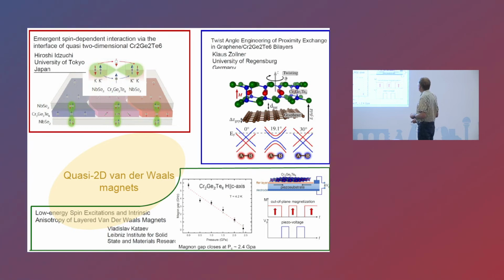Another interesting application of the single layer of chromium germanium telluride was discussed by Klaus Zollner from the University of Regensburg in Germany, where he showed that when this layer is put on the graphene layer, and the twist angle between these two layers is changed, it leads to a very interesting change in the band structure of the graphene, where the Dirac cones could be gapped. This could change the topology from trivial to non-trivial and back. That was in fact a very interesting functionality of this chromium germanium telluride layer.